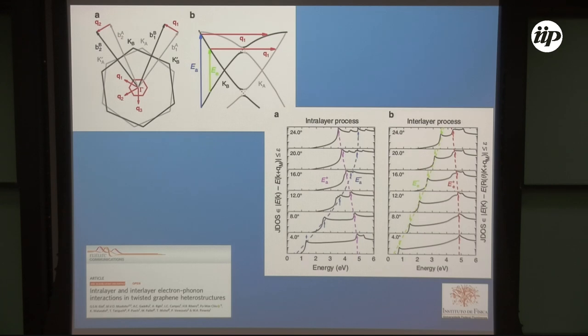And these two cones vary with angle, okay? With zero angle, we have a certain geometry, but then they vary. For instance, here is the origin, you can see the origin of the electron singularity here, okay? So just by calculating this density of states, we have this joint density of states defined here, okay? And we can see the two main peaks, okay? For these two processes, intralayer and interlayer. So those curves are the energy for these two processes.